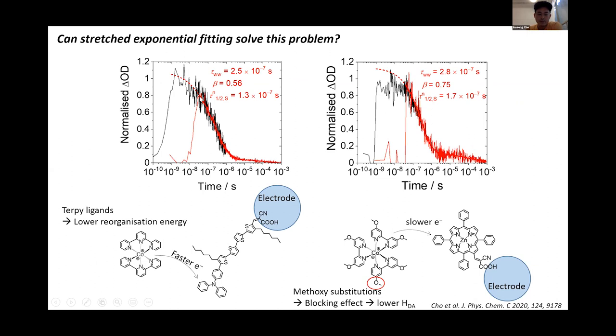So basically, if I fit this red region, which was measured only with the nanosecond TA setup, using these two donor acceptor pair. Again, there's an alkyl chain substituted on the acceptor molecule, but in this case the donor molecule was different, having a different ligand structure, so that we generate a change. So we have fast electron transfer. It doesn't show an initial plateau, but somehow the decay was well predicted by the stretched exponential fitting. So it improves the result.